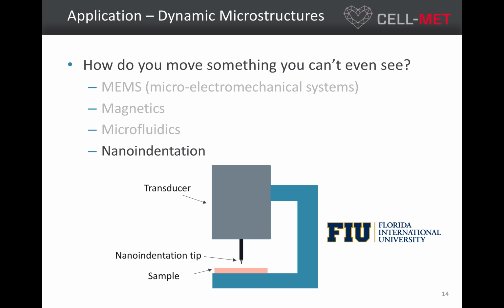Finally, our collaborators at FIU have a nano indenter, which can be stuck inside a really powerful microscope, and we can watch how our structures are deforming under pressure. And so this will be very helpful in characterizing mechanical properties, seeing how it's different from the bulk material or the material at the macroscopic scale that is typically tested when you do any sort of characterization.